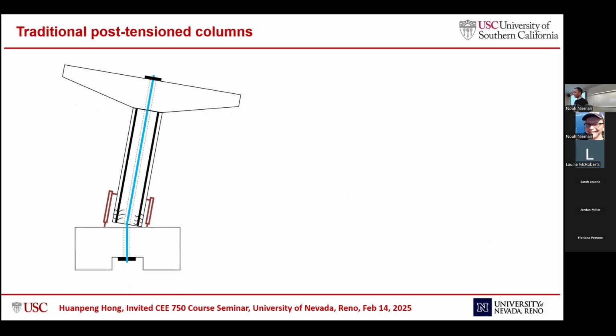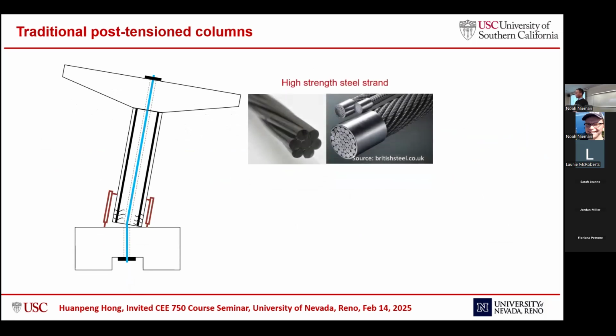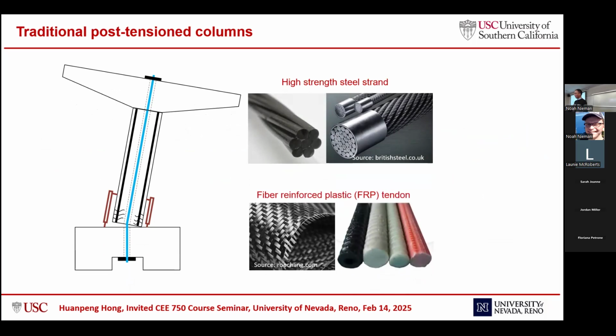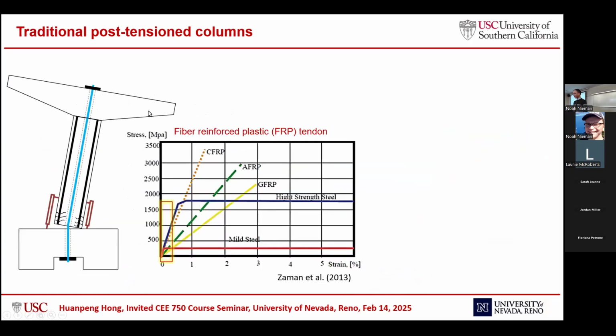So here's the traditional post-tensioned column. For traditional post-tensioned columns, we can use high-strength steel strands or fiber-reinforced polymer (FRP) tendons, such as this blue line in the schematics. The limitation of the traditional methods is that for the FRP or high-strength steel tendons, even though they have really high strength, we only use the elastic range of it, because after the elastic range, the FRP may fracture or the high-strength steel may exhibit plastic deformation. So only the elastic region is effective.